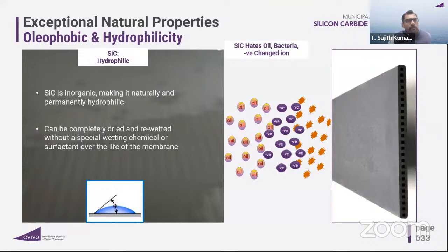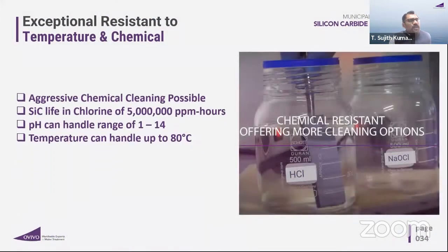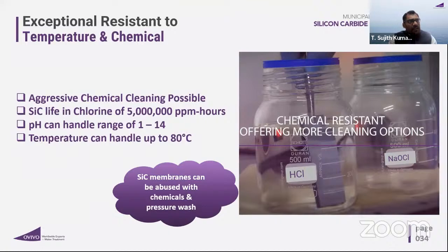The particles around the membrane, in the submerged condition, you'll see the particles are negatively charged. The fouling propensity will be very less because the particle around the membrane is negatively charged, and the membrane is also negatively charged. It tends to repel. And it has got an exceptional resistance to temperature and chemical. It can handle up to 80 degree temperature. It can handle pH 1 to 14. And the chlorine ppm hours is 50 lakhs. We are talking 10 times more than the polymeric. Whereas in polymeric, you can't go beyond 5 lakhs. Here we are talking about 50 lakh ppm hours.